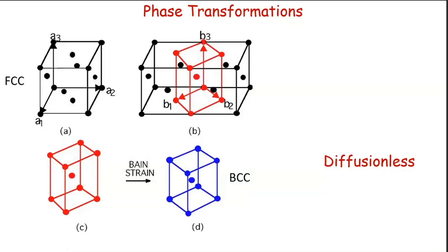Let me tell you, this is not unique. You have many such environments, but it so happens that this is the closest in terms of its volume, the total change in volume. So this is a structure that's already very close to the final BCC structure. All you have to do is sort of squash it along the C axis. This is a tetragonal cell. You squash it along the C and stretch this A and B, if I'm to call this A and B. So this is delineated. You've taken it out and you stretch these two and squash it. You come right away to the BCC structure. So without having to break and diffuse the thing, you can still get the original structure.